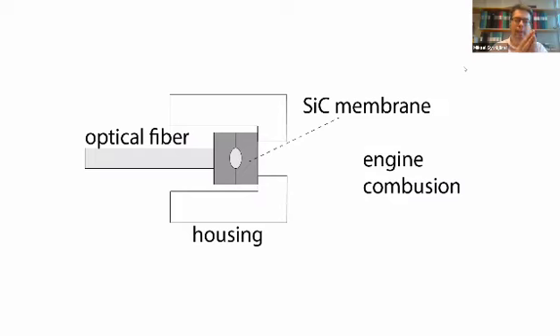And the idea is that we take this membrane and we place it in an engine and we explore higher temperatures than conventional, then we can save the fossil fuel. So then it becomes more efficient. And then when the engine is working, this is changing the cavity. And then they have an optical fiber which is monitoring this. And this membrane should be placed in a housing which is put into the engine. So then we came into another avenue about bonding silicon carbide at high temperature to each other.